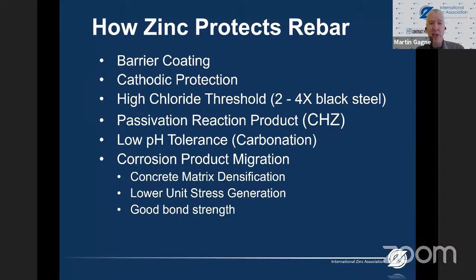While bare steel passivates at high pH, the probability for corrosion increases at lower pH. This is opposite for zinc. It has a much higher corrosion resistance at a neutral pH. So as the carbonation front approaches galvanized reinforcing steel, the corrosion resistance is actually increasing.